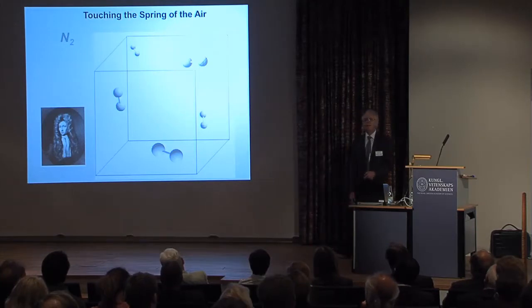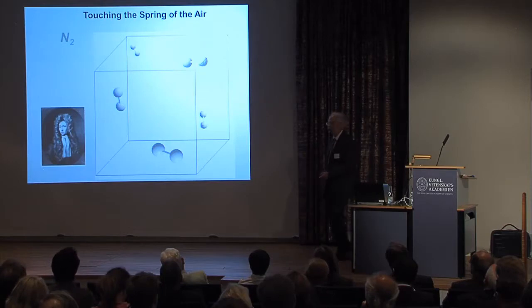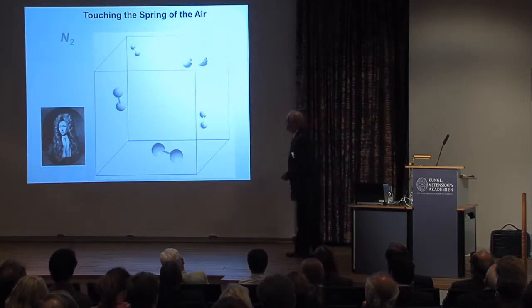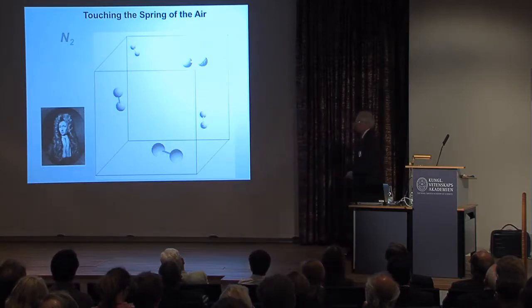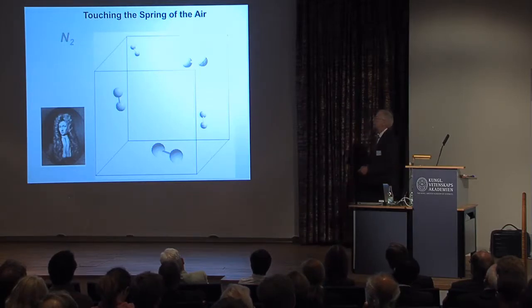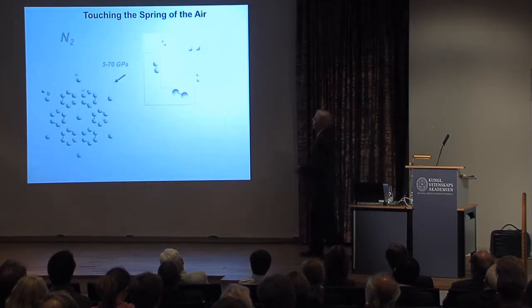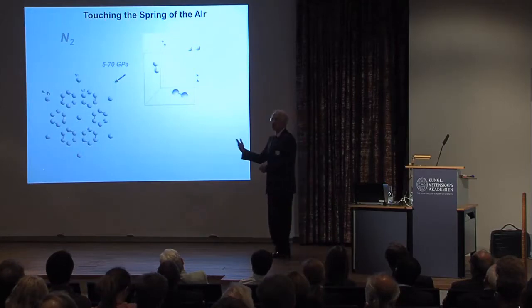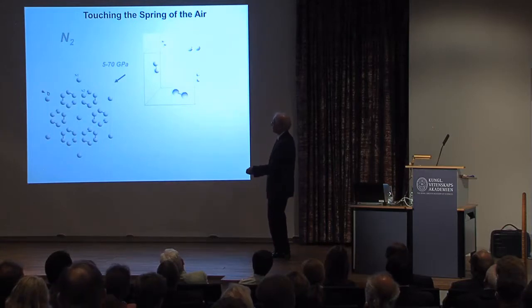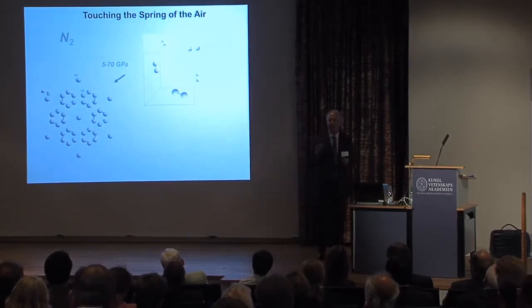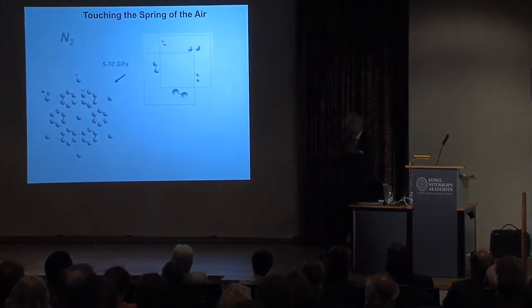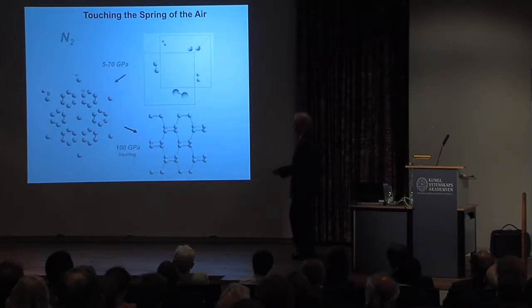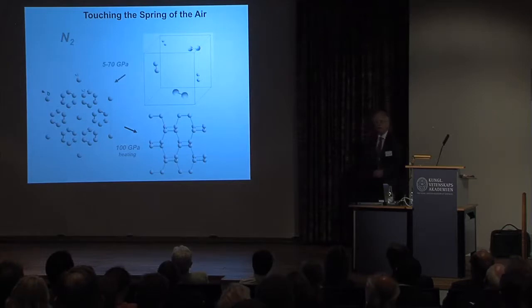So let's look at a couple of examples and return to what Boyle called touching the spring of the air and consider the most abundant component of the atmosphere, nitrogen, which, as you know, consists of these diatomic molecules with a very strong triple bond. With increasing pressure, one finds, as one sees in the simple paradigm, there's pressure-induced freezing on a lattice. The molecules are still intact, and actually, with increasing pressure, these molecules rearrange in various ways. But ultimately, at about 100 gigapascals, or 1 megabar, with some heating, you see a transformation.